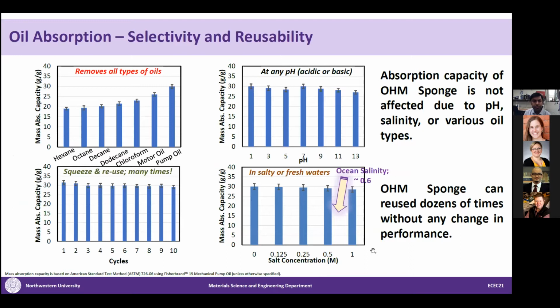We have done many tests using this OHM sponge for selectivity as well as reusability. So as you can see in this plot, the y-axis is mass absorption capacity, which is nothing but the ratio of the mass of absorbed oil divided by the mass of the sponge. Depending on the different kind of oil, the OHM sponge can absorb almost 30 times its weight. And we have used all sorts of synthetic and processed oil, from hexane to pump oil, and we have seen it goes from 20 to 30 times its capacity.